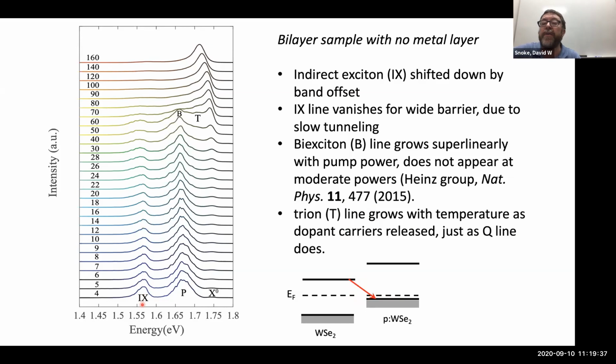And there are other things that really easily identify the indirect exciton. Like I said, it has a much longer lifetime. So we do time resolved measurements with the streak camera, and you see that it has a very long lifetime. And the other is that it's hypersensitive to the thickness of the barrier. Remember I said the exciton binding energy is not especially sensitive to that thickness because it's just the Coulomb distance. But the tunneling rate for recombination through that is exponentially sensitive to that barrier thickness. And so if the barrier is too thick, you see no indirect exciton.